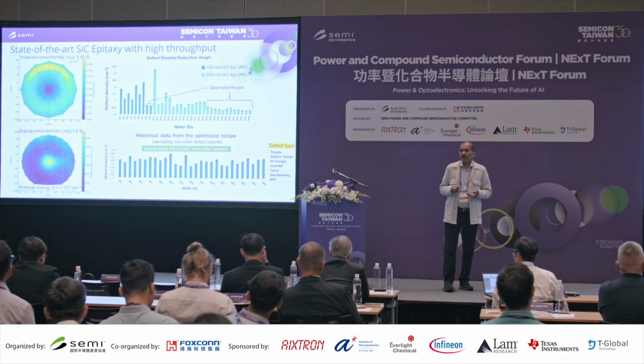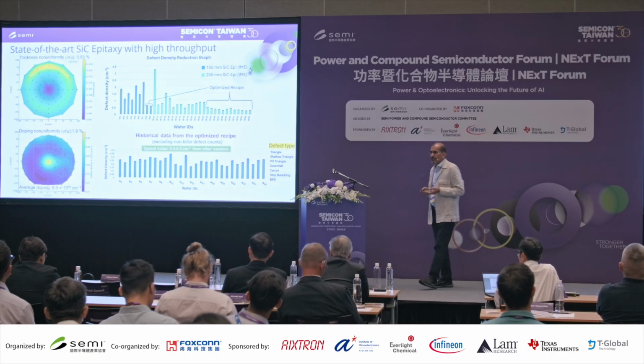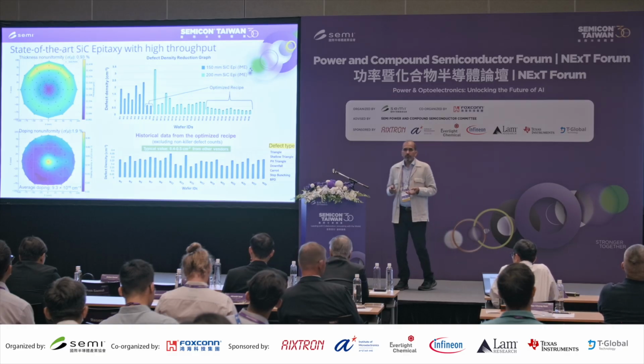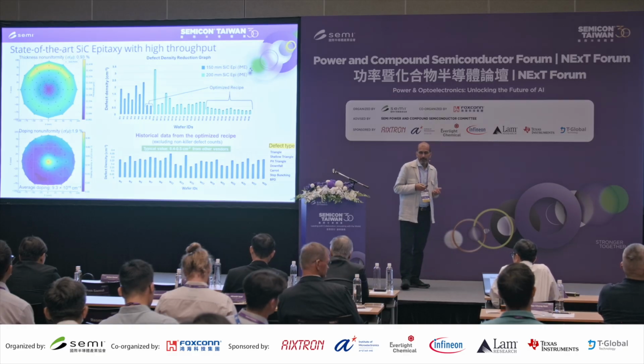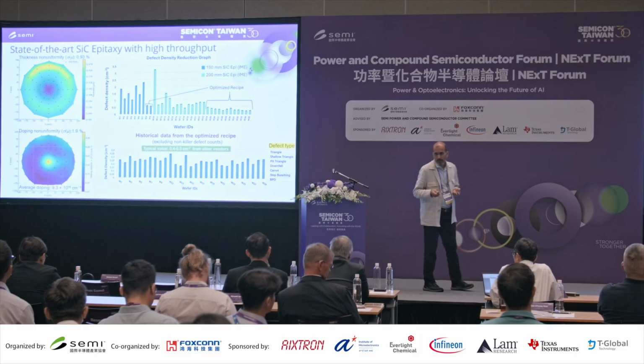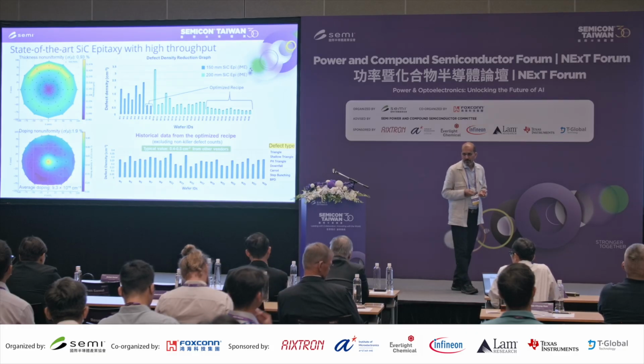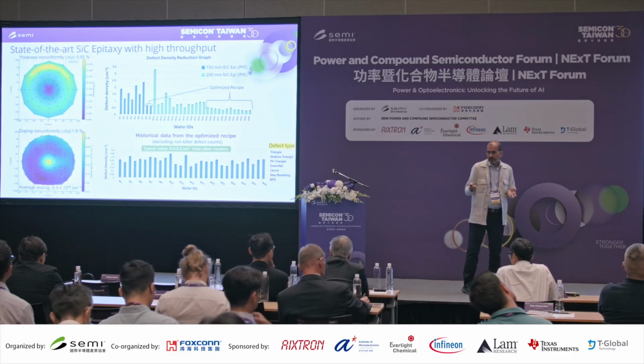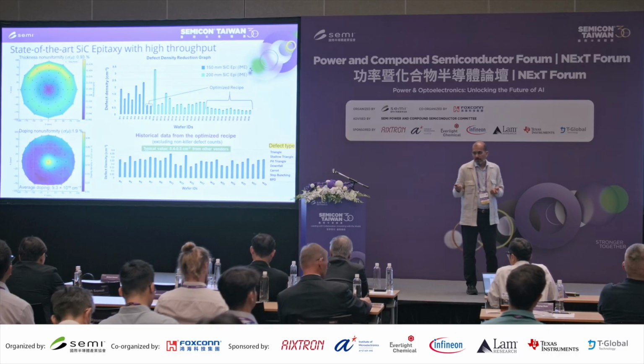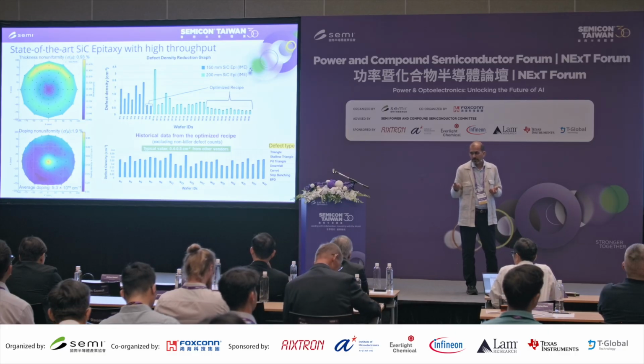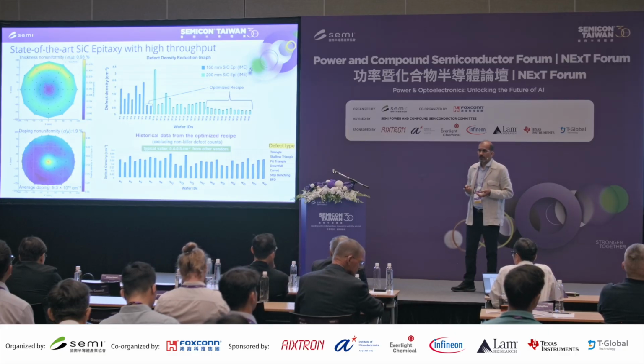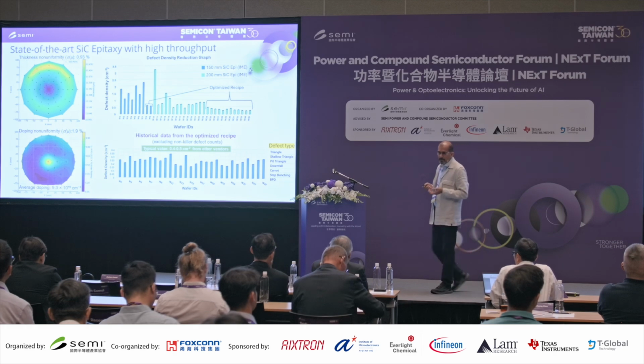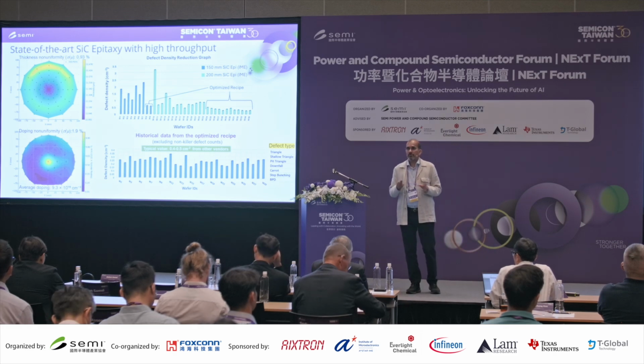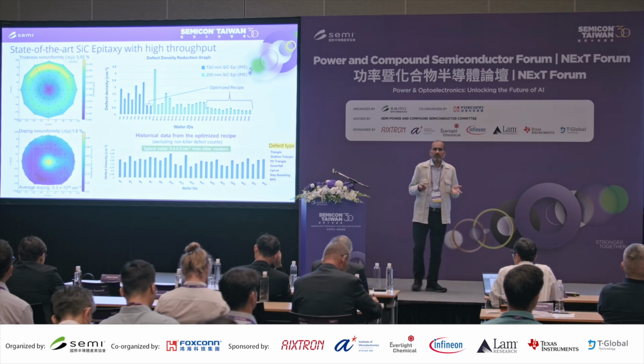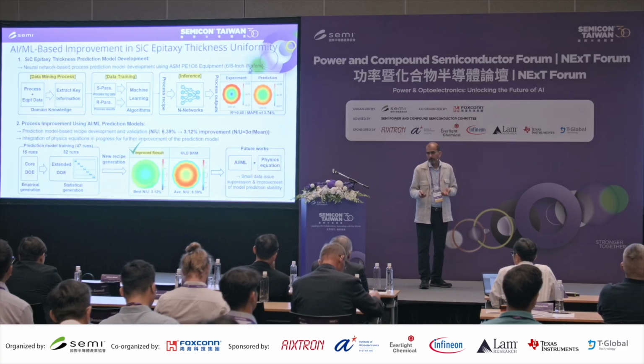At the same time, we implemented AI machine learning for improving the thickness and doping uniformities. Look at the top left graph here, which shows our thickness uniformity. 1 sigma uniformity is better than 1%, so 3 sigma is about 3%. I would say this is best-in-class thickness uniformity for silicon carbide.